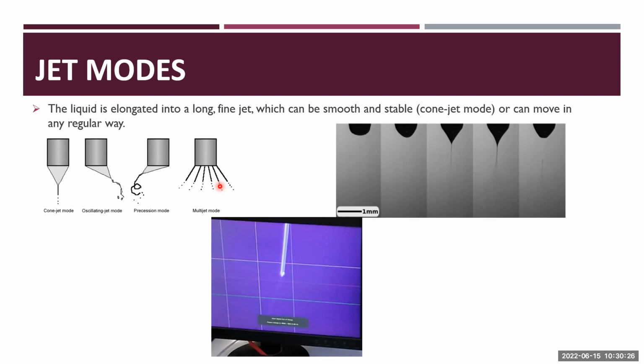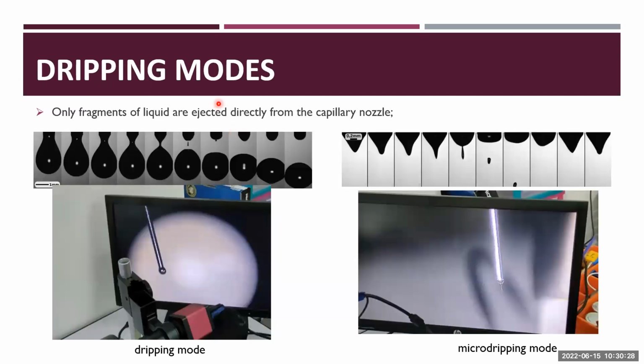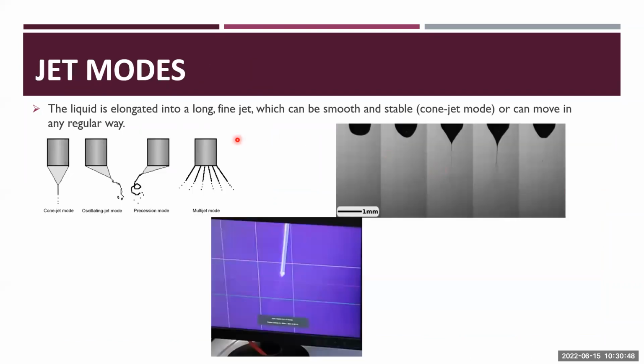value. So when we are talking about millimeter scale, usually we work in the flow rate in mil per minute. But when we are talking about micro dripping, usually it's in mil per hour, like 1-2 mil per hour, or let's say up to 5 mil per hour. But when we are talking about nanoparticle production, we are talking about microliters per hour, usually below 1,000, like below 1 mil per hour.